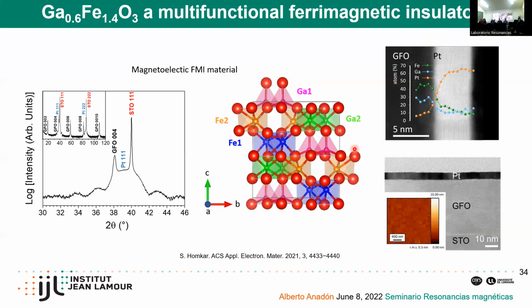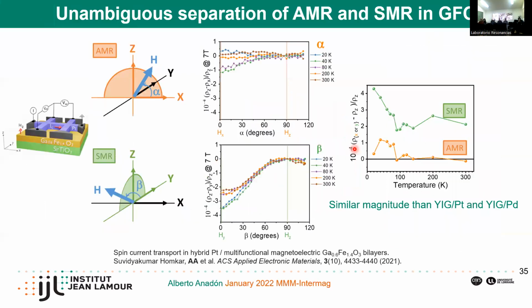So the first thing that we did when we got these samples was to study also the spin Hall magnetoresistance in the system, because this can give you an idea of how good is the material in terms of spin current generation. So we observed that the spin Hall magnetoresistance is comparable to the one in YIG when we put this GFO system in contact with a platinum top layer. And we observed also that the proximity effect in platinum could lead to anisotropic magnetoresistance, and we observed that these are not very important, especially at higher temperatures. So spin Hall magnetoresistance basically dominates all the magnetoresistance in the system.